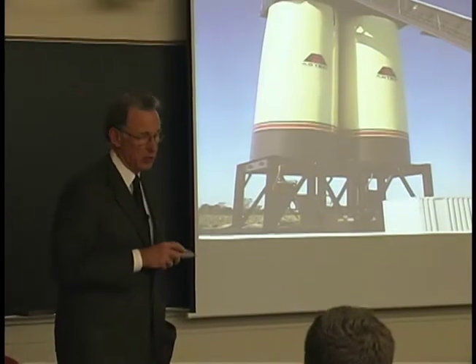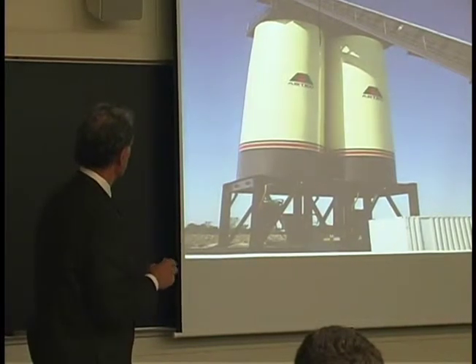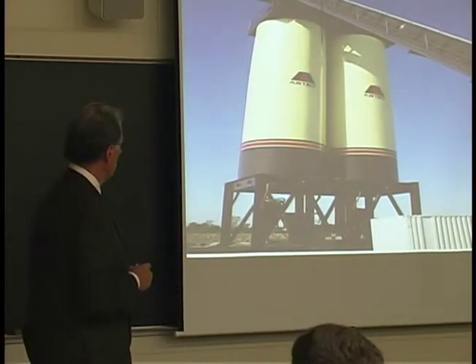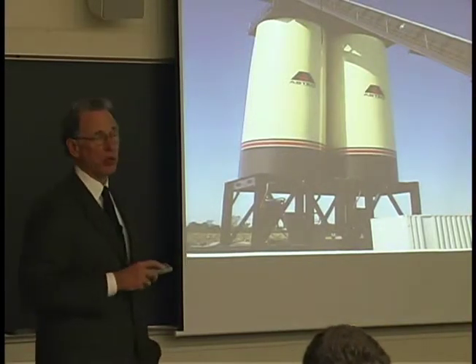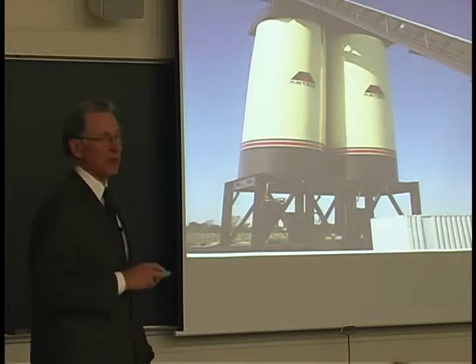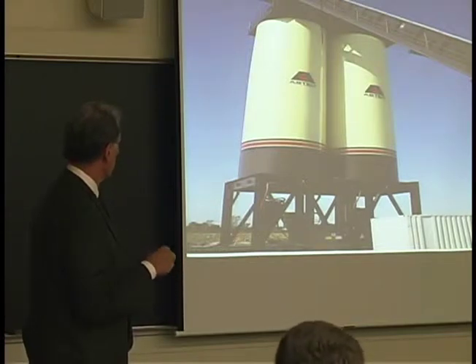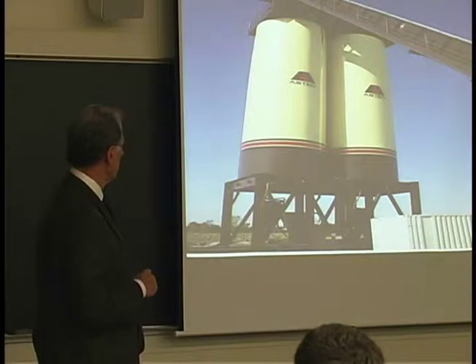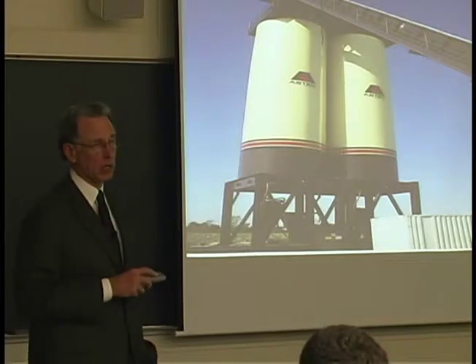We are able to store hot asphalt for a certain period of time, because these again have pipes around the outside. The state of Illinois would allow us to keep asphalt in these storage containers for about 24 hours, but most contractors don't like to store asphalt that long. We can store it here if you have a shortage of trucks for a while before you can stop the process, and the trucks will pull under here, and then we can load them quickly and get them out. But by and large, in Illinois, you don't store that asphalt more than a couple hours.